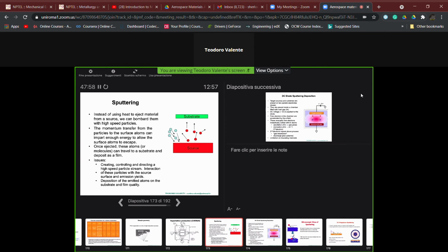As we said, instead of using heat to evaporate materials, that is to eject materials, we can bombard the surface with high-speed particles. These high-speed particles are typically ions. The momentum transfer from these high-speed particles, which impinge on the surface, gives enough energy to allow the surface atoms to escape. And when these atoms have been ejected from the surface, they can travel to a substrate and they can deposit in a film. So we do not have evaporation, we just have atoms which are ejected due to a mechanism